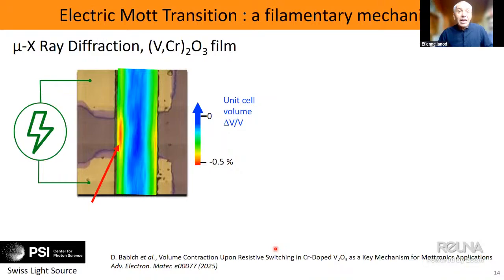So this was the electronic part, but we also tried to understand whether this transition has some consequence from the structural point of view. For this, we have done micro X-ray diffraction. Here, I show you an example. This stripe at the center corresponds to a thin film of V2O3 that we have deposited. And in yellow, you have the two electrodes, and we have applied an electric pulse to induce a non-volatile transition.